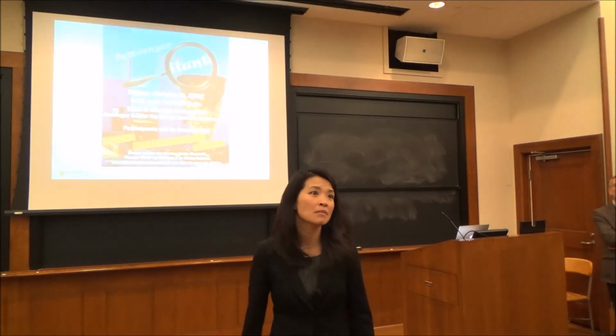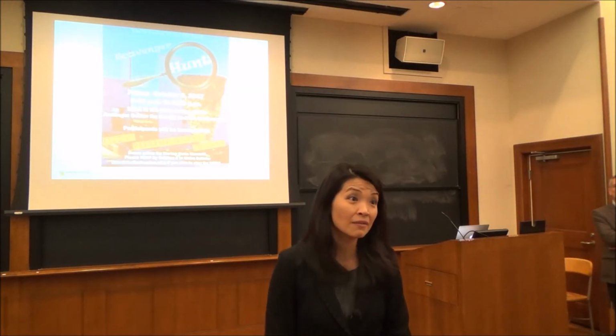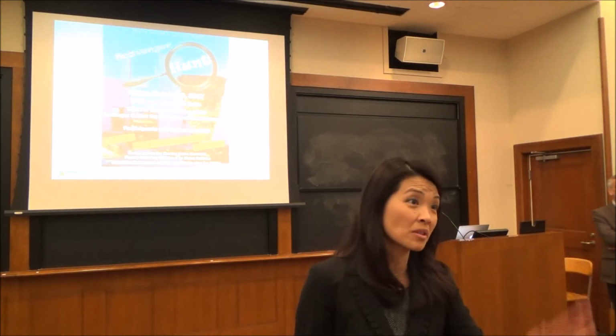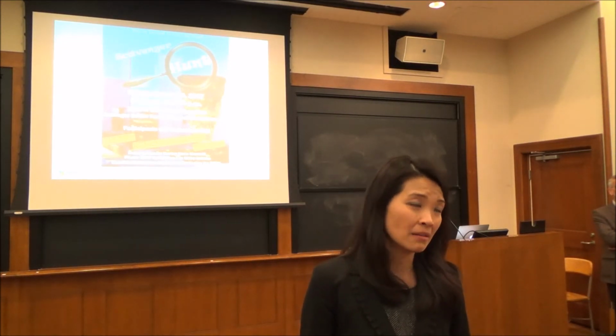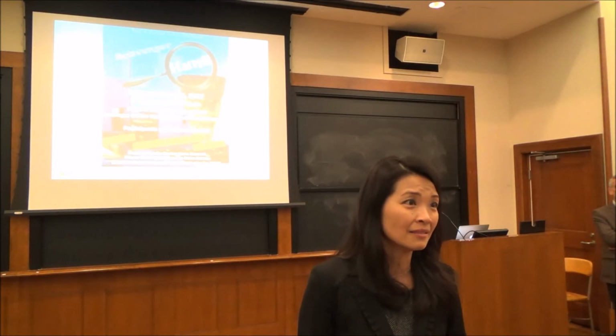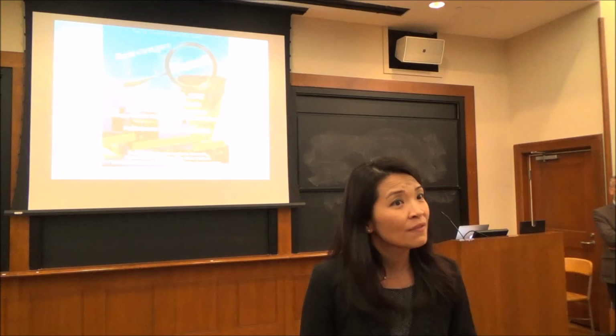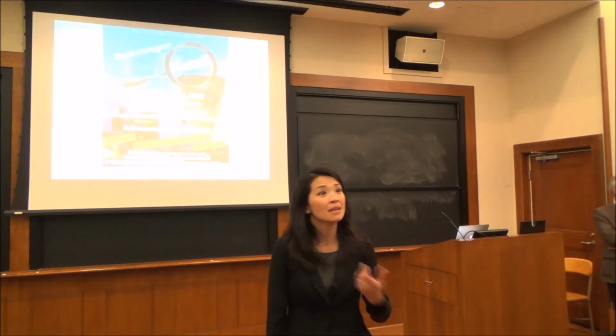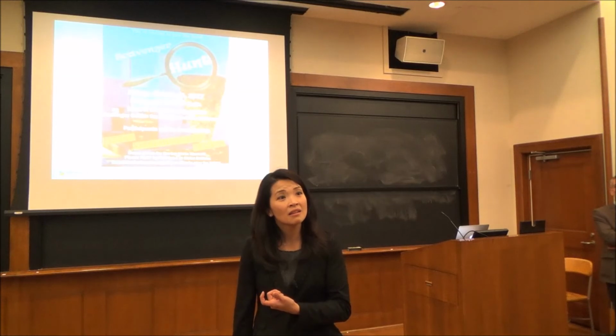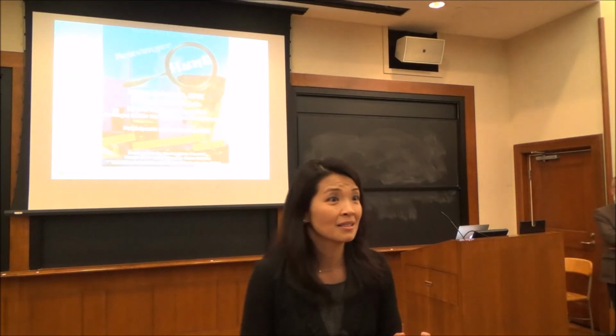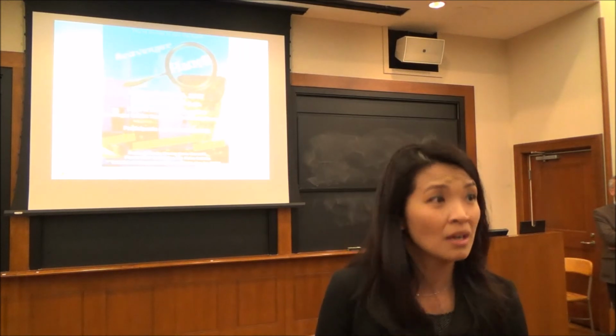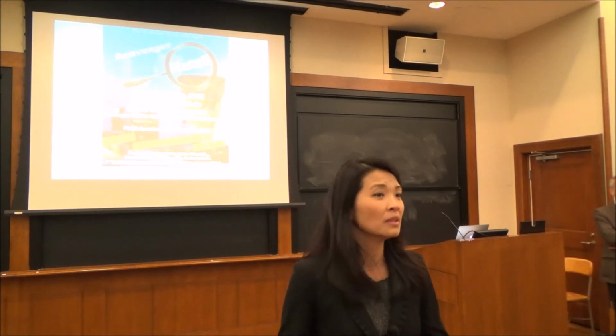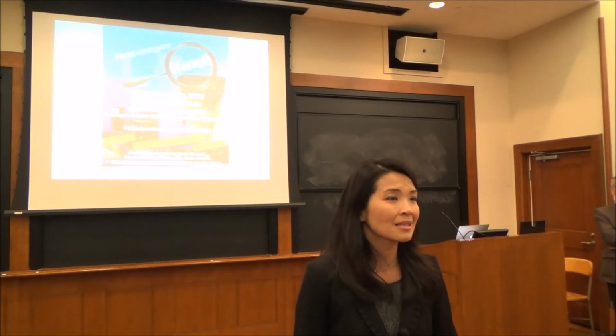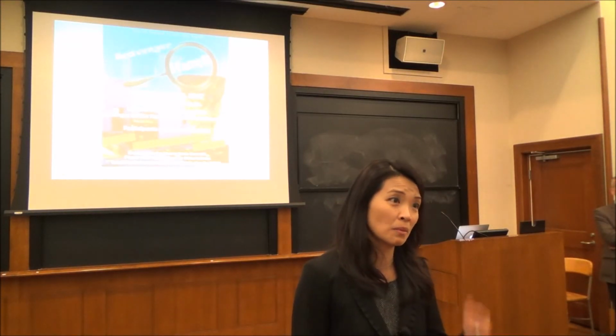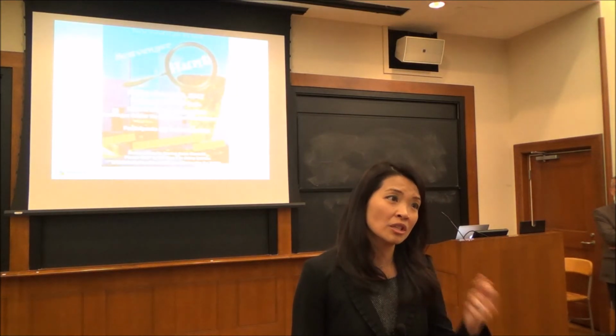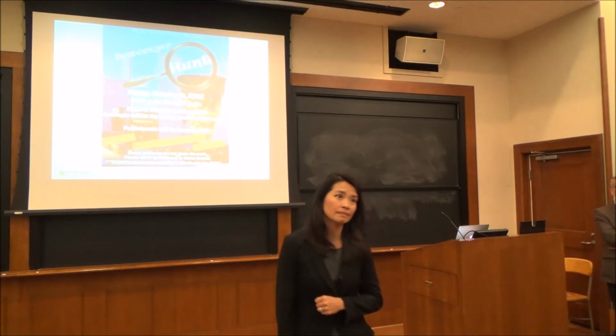No, we've not. We wanted to stay with the organics because then we can tune it. In fact, what we'd like to do is to tune it so that it further absorbs into the UV. The nice thing about organics is that once you get a handle on the chemistry, you can tune it and move it around. There are others in the community that have demonstrated near-infrared solar cells. Those voltages aren't as high as ours because they absorb low energy photons, but they generate more power, if you will. So it's all a trade-off. We decided we want to go with the more energetic photons. We wanted something with which we can generate enough power to power our smart windows.